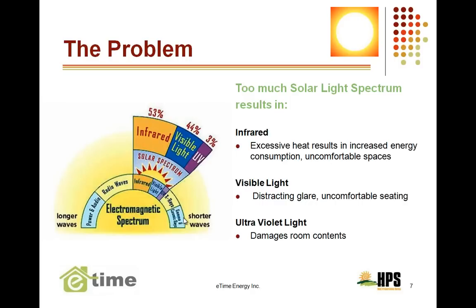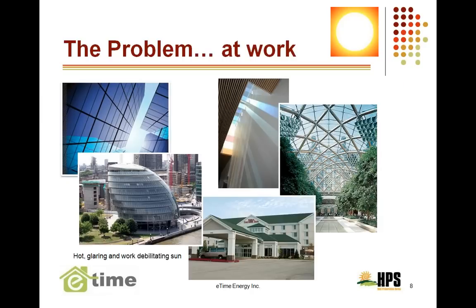What our coating is doing is being able to isolate out the infrared rays and also the UV rays. And in the infrared spectrum, we pull anywhere between 40 and 60%, depending on the level of coating that we put on it. That's not the thickness, that's just the different types of coating. I'll explain that in a minute. The 3% of UV, we're blocking out about 90+% on that. So the ideal of what our coating is trying to do is be selective as to what components it's taking out of what's penetrating inside the envelope. And the 44%, we're trying to hold as much of that as possible. So typically we see a reduction of anywhere between 15 and 20% on the envelope with respect to the visible light. But that's atypical. Even a window will take away 8% of the visible light coming into the facility.